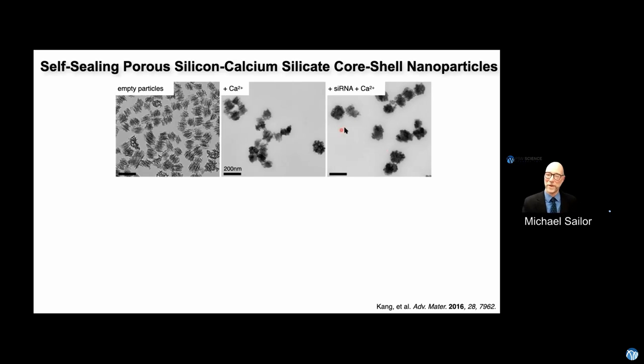And here's an example on the far right of the same basic chemistry, but now with nucleic acid, siRNA. You see we still get the same basic type of nanoparticle, but now it's glued in. When we analyze these things, we can see, again, about a 20% by mass loading of the nucleic acid inside our nanoparticles. So it really worked well.